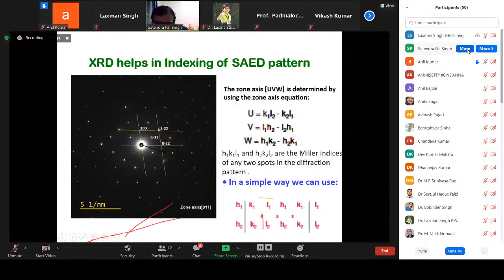The zone axis UVW is given by this: select any two diffraction spots and their corresponding HKL values, and obtain UVW using this relationship. U is equal to K1 L2 minus K2 L1, V is L1 H2 minus L2 H1, and W is H1 K2 minus H2 K1. So from any two diffraction spots you can obtain the zone axis. Or in a simple way, you write the two diffraction indices, H1 K1 L1 twice and H2 K2 L2 twice, and then do the determinant. Leave the first one, then select the next.